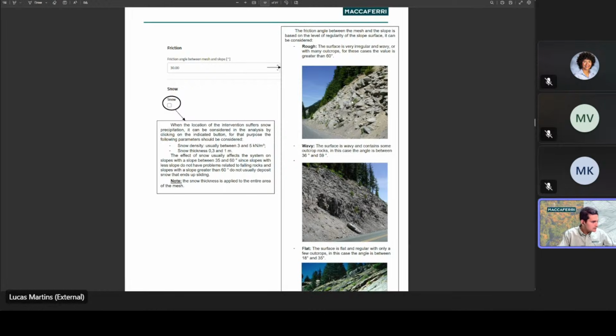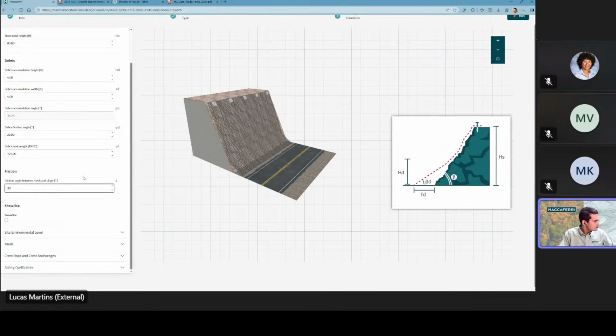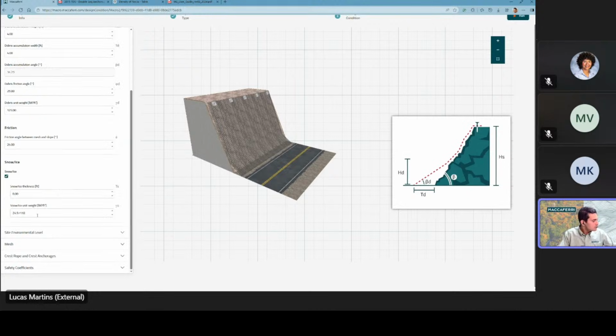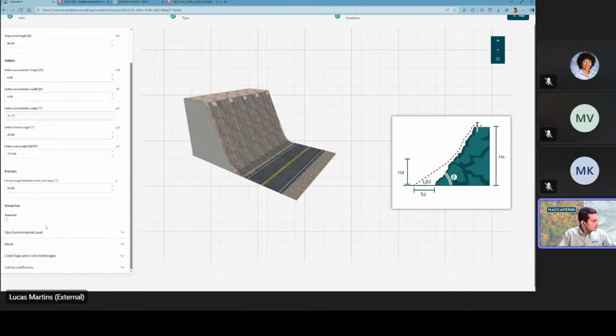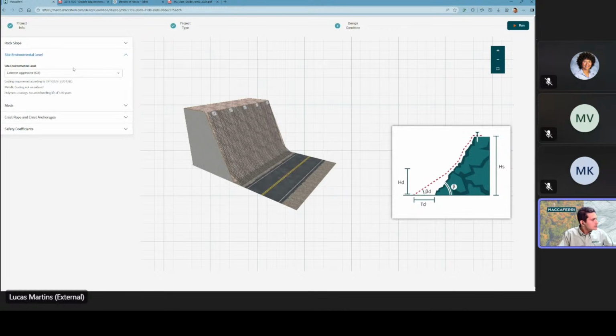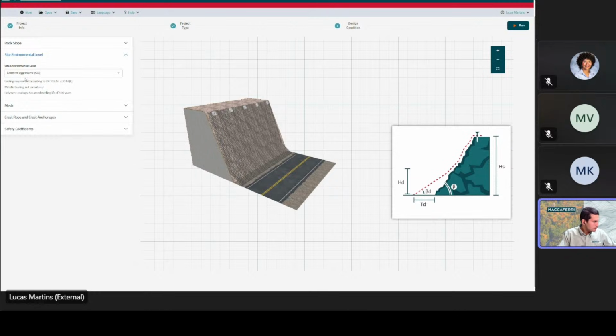If you want to dive a little bit deeper into this, you can go into the WSDOT guidelines and they explain it a little longer. But for the sake of time, let's go here and enter a flat slope. So very little resistance against that slope. Here's where you'd consider snow accumulation if you want a snow or ice thickness on top of your mesh. For the site environmental level, this is a European norm, but it kind of gives you an idea. For different sites, for different environmental levels, you have different corrosion requirements. Here on extremely aggressive, you'd only be considering something with a polymer coating.